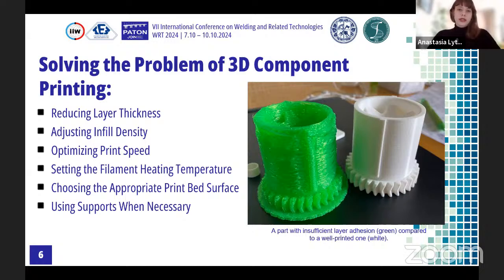To resolve any problems that can occur, it's better to always reduce layer thickness, because thinner layers can improve adhesion and reduce deformation. And adjust infill density, because it reduces internal stress. Optimize print speed: you need to consider that a slower print speed helps avoid material overheating, because each layer has more time to cool down. And adjusting the heating temperature is also very helpful, because high temperature can cause material melting. The correct platform surface helps to avoid deformation and delamination of the bottom layers from the print platform.